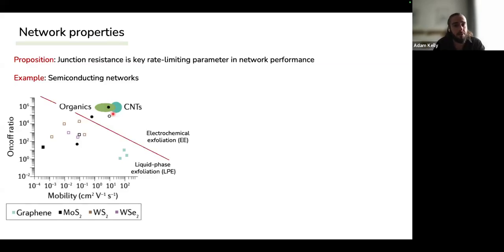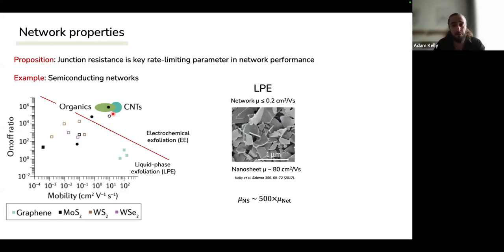But if we look a little bit closer, what we find is that the electrochemically exfoliated nanosheets tend to perform much better than the liquid phase exfoliated ones. Now, if we actually look at the networks, the reason for this becomes very, very obvious. This is an SEM image of a liquid phase exfoliated network. What we find is that the nanosheets are quite thick. They're kind of jammed in and sticking out on top of each other. And when we look at the mobility of the nanosheet, it tends to be much, much higher than the mobility of the network.